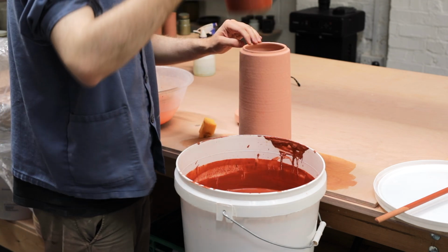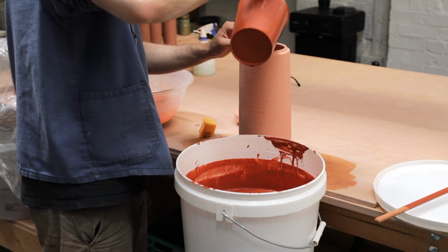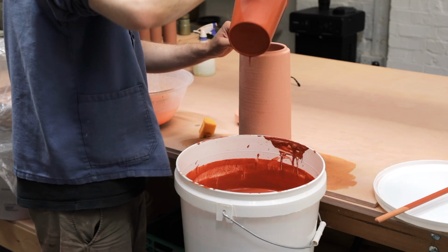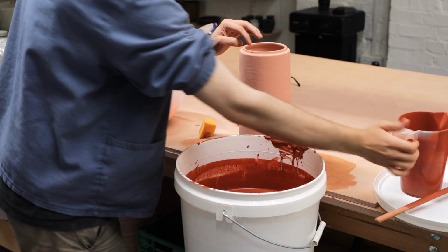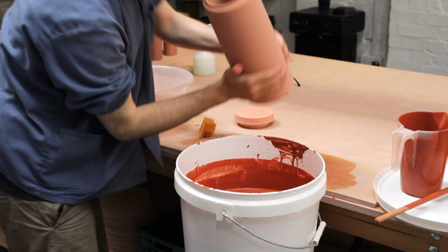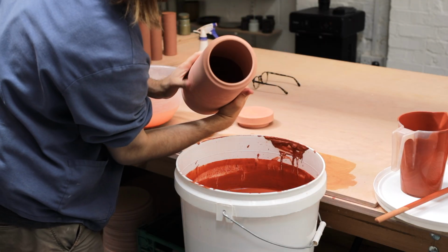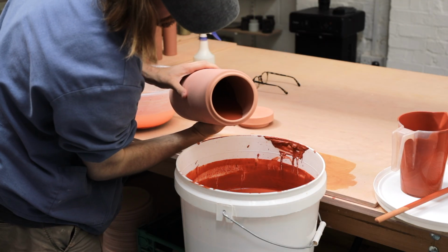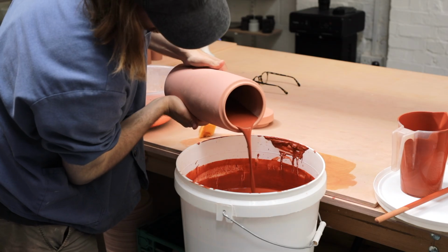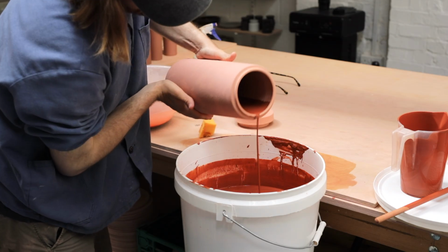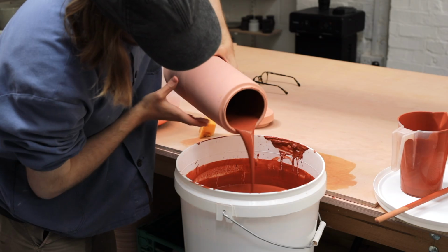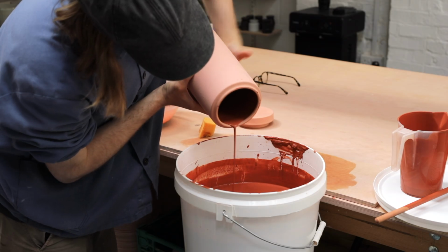If I attempted to do this immediately after glazing the outside, the walls of the pot that are already saturated with water wouldn't be able to absorb any more water, and thus the raw materials wouldn't be able to really adhere to the inside form. This would mean that the glaze ends up staying wet for far too long without drying, and eventually it would just crack and fall off. And this is why the day's wait in between is so important.